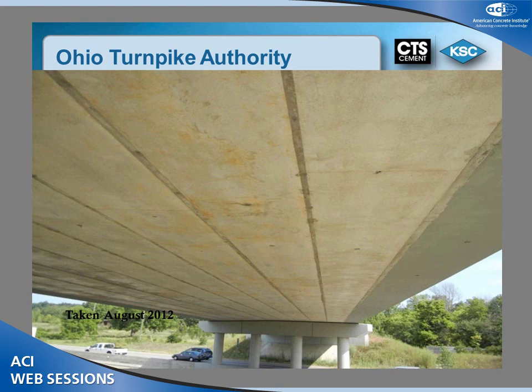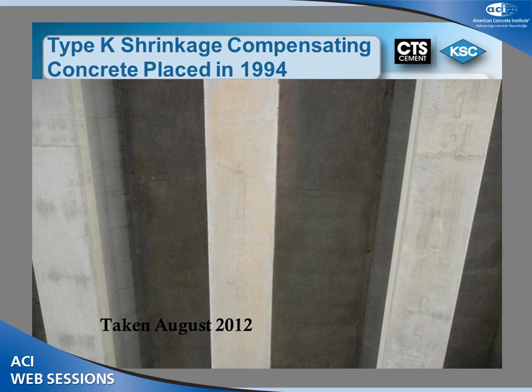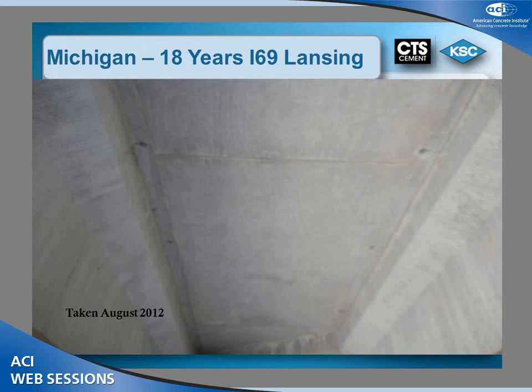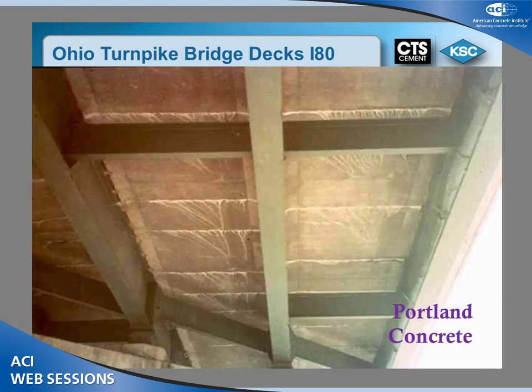this is a picture of the Ohio Turnpike Bridge. This bridge is only a few years old, but you can see that it's in pristine condition. There's no cracks in this deck. This one here was placed in 1994, and you can also see there's no cracks up here. Now, this particular picture here is a concrete girder system, whereas a lot of the bridges in that same region are steel girders. This is just a closer picture of the same type of structure, 18 years old, on I-69 near Lansing, and we can see no cracks in the concrete. This is an interesting thing. This was done in Brown County, Ohio.